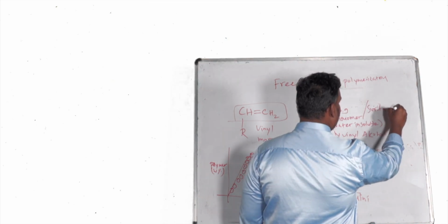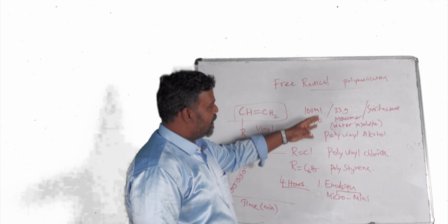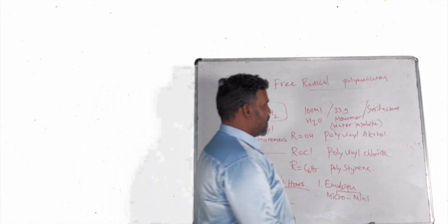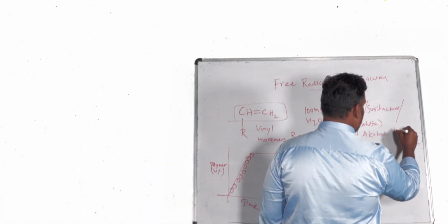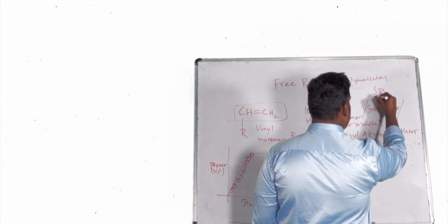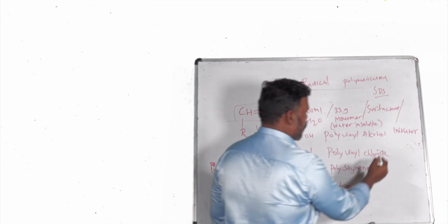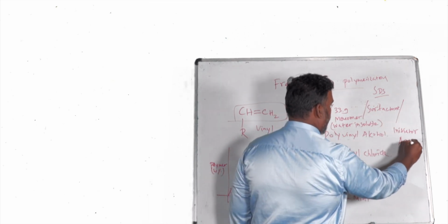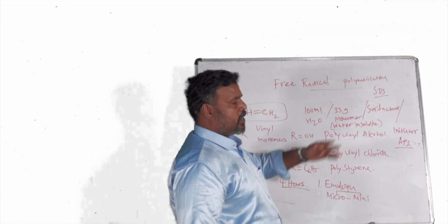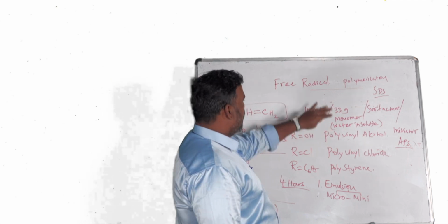You're also using surfactant to prepare the polymerization, so that it is very nicely emulsified. When you add all of it and the temperature is right, you can add an initiator. I have drawn a structure of the initiator. The surfactant can be sodium dodecyl sulfate, one of the most famous traditional surfactants. You can also use initiators like APS, ammonium persulfate, or potassium persulfate. You can take any monomer, water-based monomer, or water insoluble monomers, to conduct emulsion polymerization.